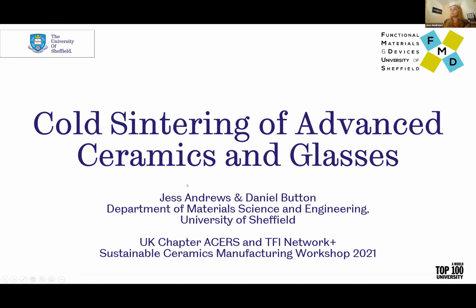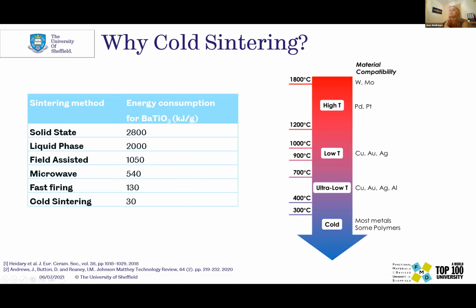So firstly, why would we look at reducing the sintering temperature of ceramics? Well, as Laura said earlier, something like 35% of costs in the ceramic industry are related to energy. And the table on the left of our slide just shows how much of a reduction you can get for sintering 1 gram of barium titanate by cold sintering versus solid state. And that's about a 99% reduction. So that's a huge impact that can be made quite simply.